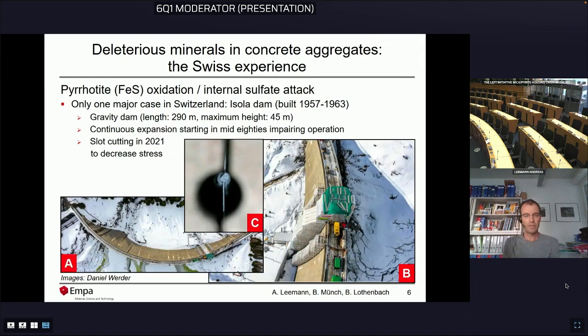So our experience with pyrrhotite or iron sulfide oxidation in general that is linked to internal sulfate attack. We had only actually one major case in Switzerland, and that's the Isola Dam built between 1957 and 63. It's a gravity dam, 290 meters long, 45 meters high. It started to expand continuously in the mid-80s, and due to this swelling, operation was impaired. So last year, the dam was cut.